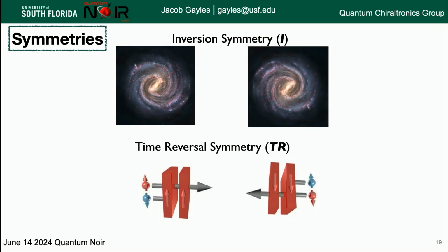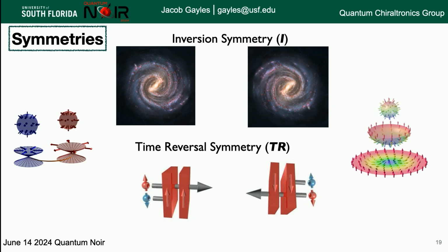What causes all of this, right? It's symmetry that causes all of this. This is how you change these different materials. So for a skyrmion, you need to break, well, you don't need to do it anymore, but when we started, you had to break inversion symmetry and time reversal symmetry. When you break time reversal symmetry, you get magnetism. And then breaking inversion symmetry allows for this chirality dependent term to show up. So you get a left or right handed chirality depending on how you break inversion symmetry.